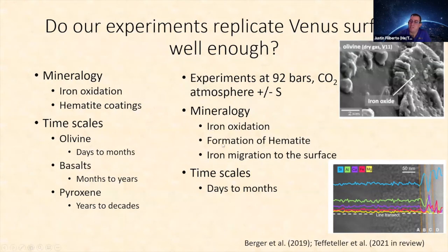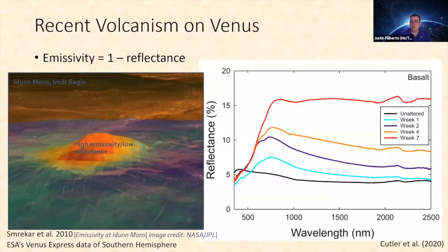Iron oxide formation of hematite. This is a TEM image showing iron migration to the surface. And again, very similar timescales to our experiments of days to months. So what this is telling us is these high emissivity lava flows, if we can use our spectroscopy as a one-point comparison, will tell us that these are years, decades, at most about 100 years old for the highest emissivity or the lowest reflectance lava flows. And that we can use these to sort of get a first order age date of our lava flows.